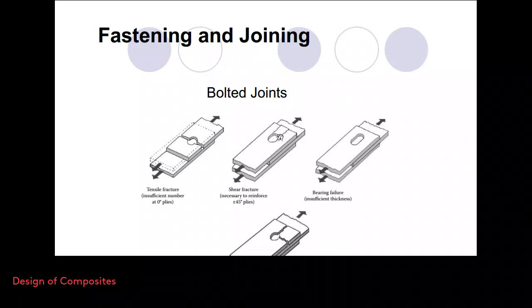And you may see a failure at the upper or lower plate. In fact, this means that the shear dominates the failure, and we know that the shear generally is carried by the off-axis oriented plies with the off-axis oriented fibers. So you need to increase the positive 45 or negative 45 degree plies, the number of plies as well.